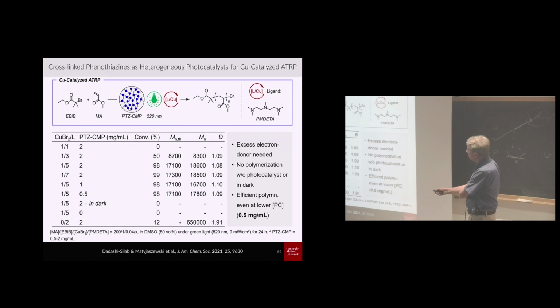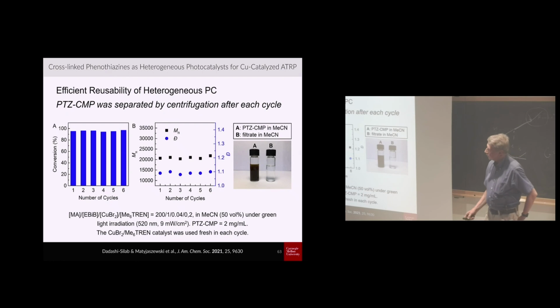If you have no phenothiazine, no polymerization. If you have no copper, you have a ligand, you have a polymerization, but you get a 650,000 molecular weight with very poor control, which means the ligand can also give a little bit to the alkyl halide, but there is no deactivation, no control, and practically uncontrolled polymerization.